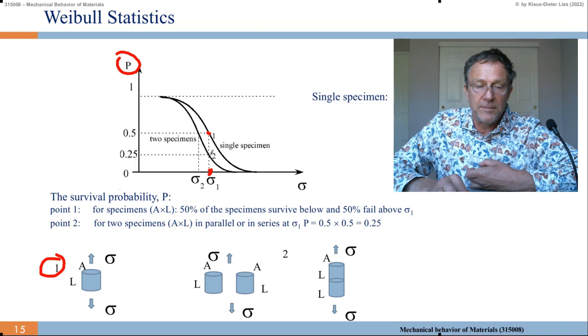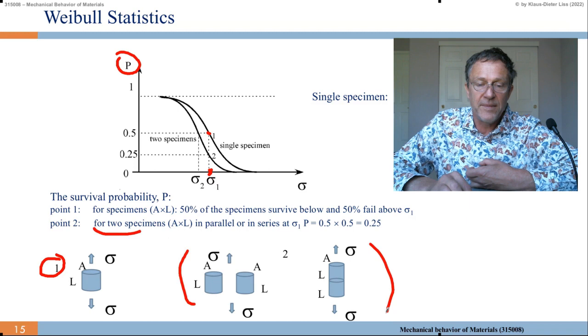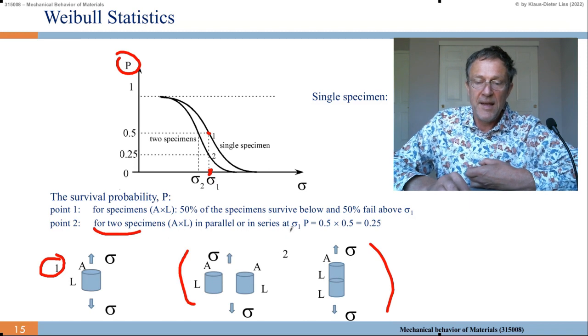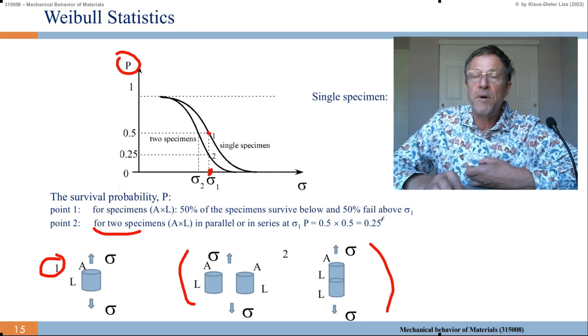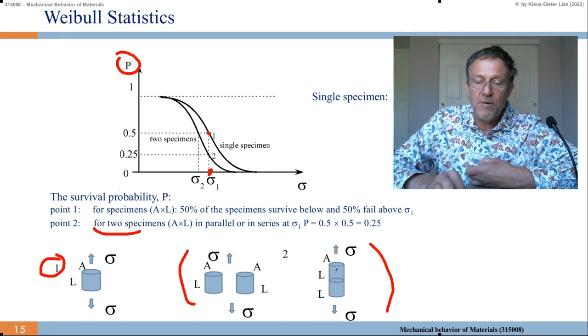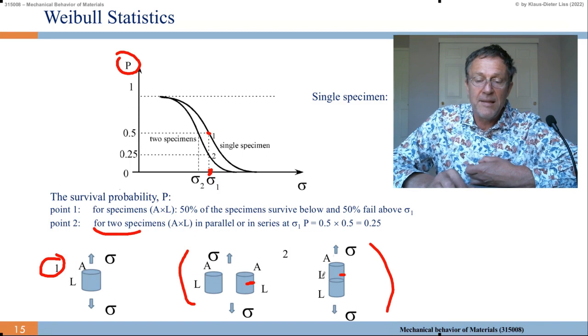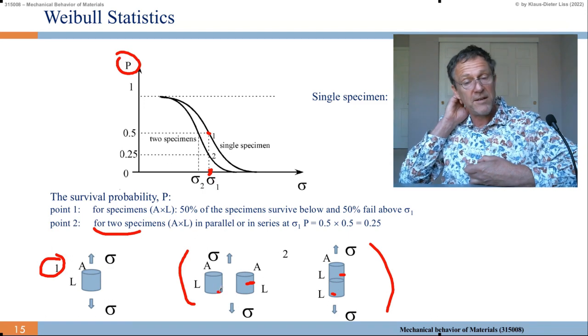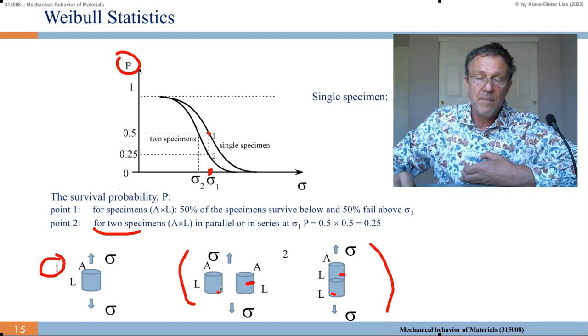And the point 2 is if I take 2 specimens, as shown here and there, in parallel or in series, then the probability at stress sigma 1 is 0.5 times 0.5, so it becomes 0.25. And in this model, it doesn't matter whether you put them in parallel or in series, because here you may have cracks. If you have a crack there, then the whole thing fails. And here as well, if you have a crack in just one, the whole thing fails. And if you have a crack in another one, also the whole thing fails. So it doesn't matter. It just goes with the volume, but not on the position of the volume.